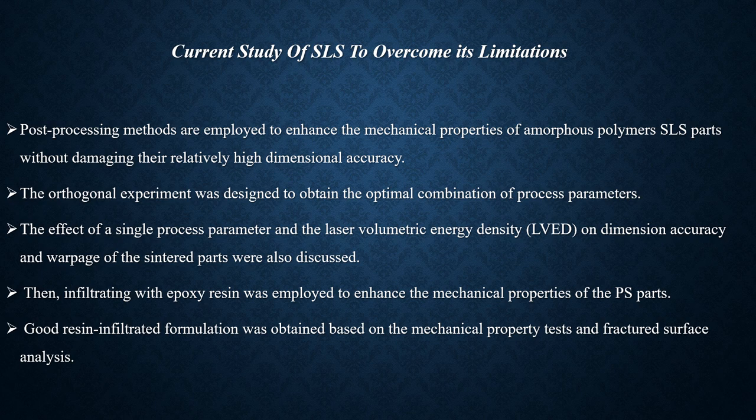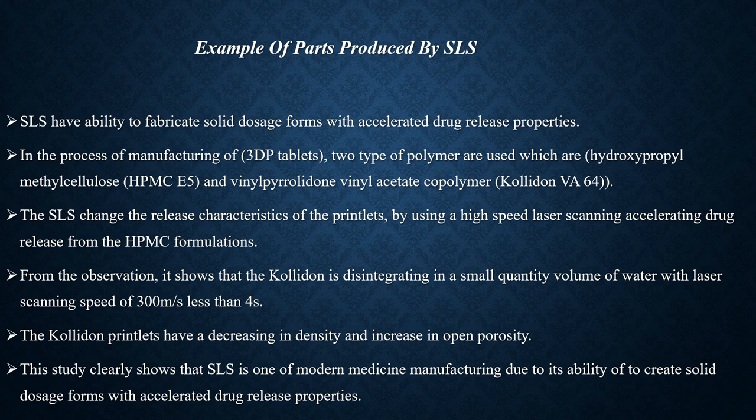It is proved based on study that SLS has the ability to fabricate solid dosage forms with accelerated drug release properties. In this study, two types of polymer are used: HPMC E5 and Kollidon VA 64. SLS changed the release characteristics of the printlets by using high-speed laser scanning, accelerating drug release from the HPMC formulation. The Kollidon is disintegrating in a small quantity volume of water with a laser scanning speed of 300 mm/s in less than four seconds, showing SLS as one of the modern medicine manufacturing methods today.